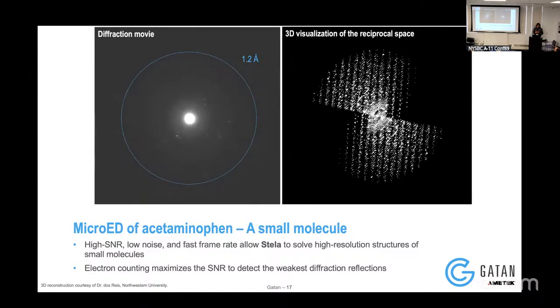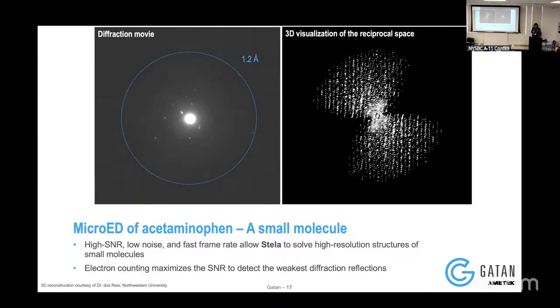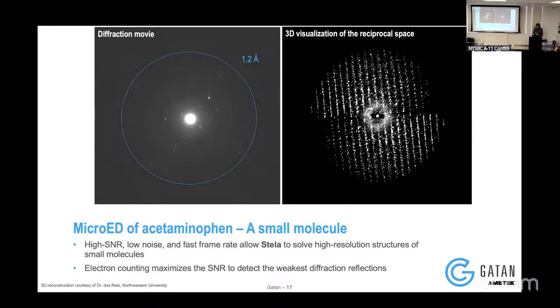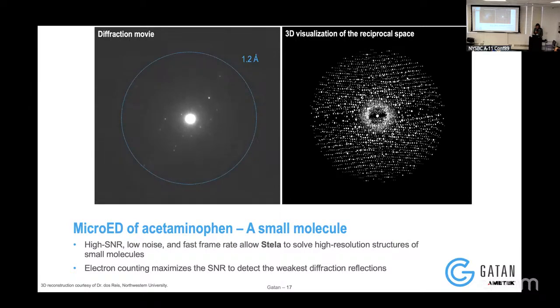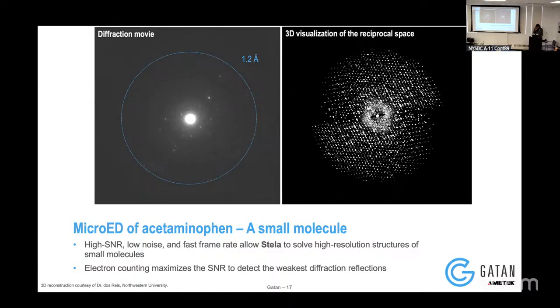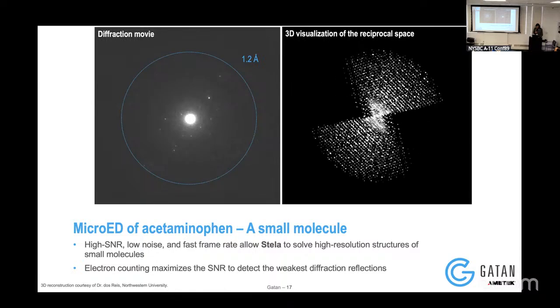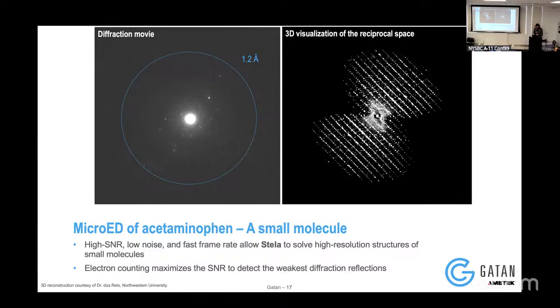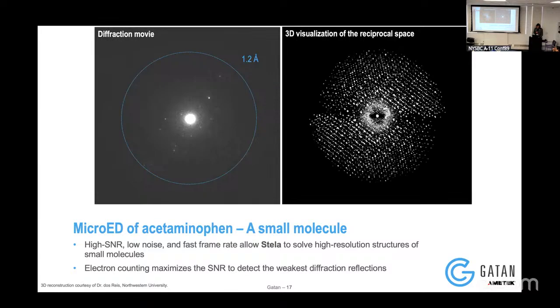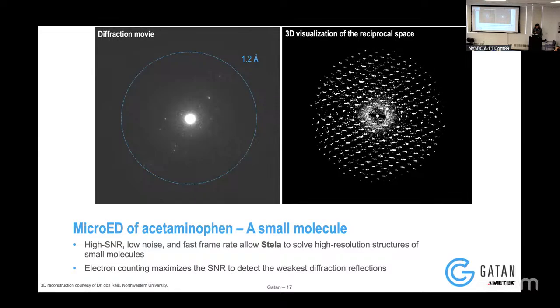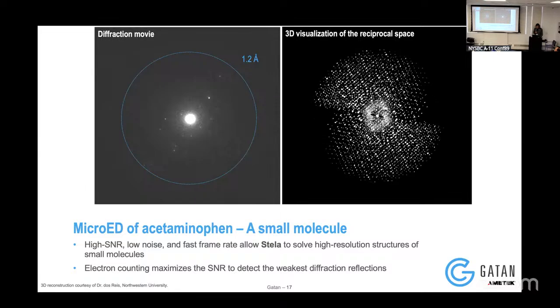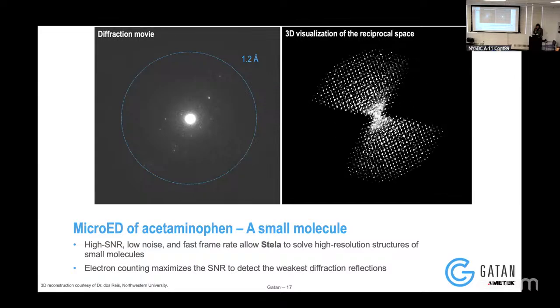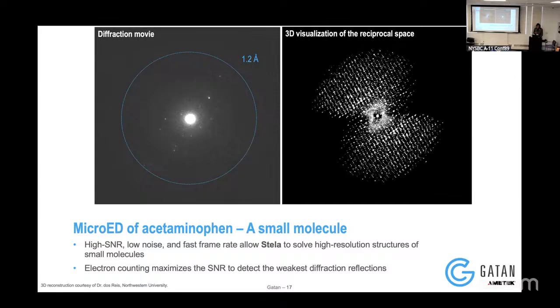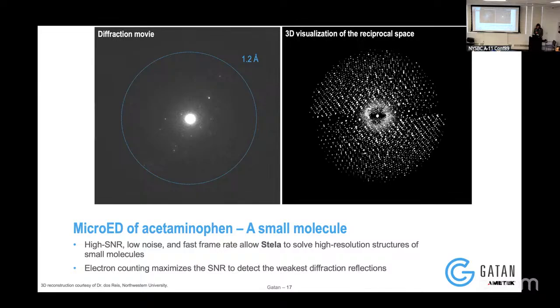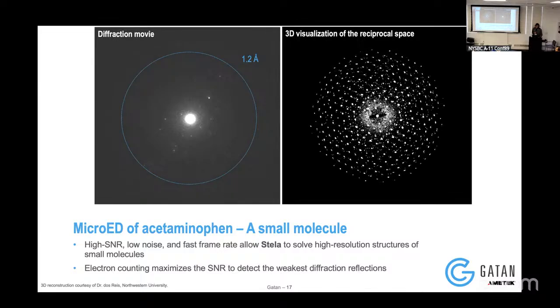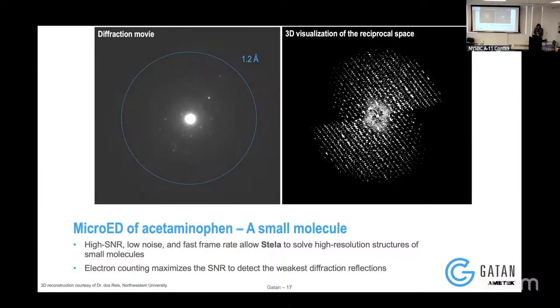Gatan will present later on, Fernando, and they have integrated our ELA detector as the Stela. This is an example from their work on a small molecule with a high signal-to-noise ratio, and the fast frame rate enabled by Stela gives you high resolution structures. The electron counting allows you to detect even the weakest reflection, and this is visualized in the reciprocal space image.